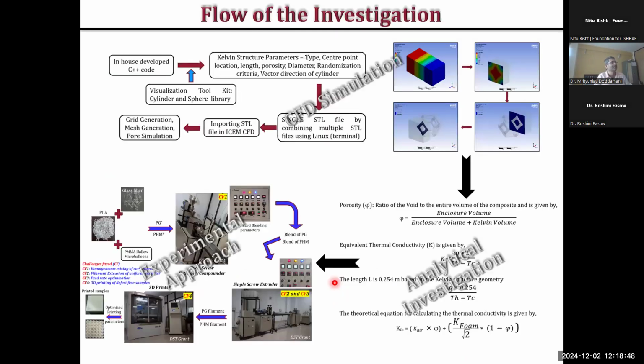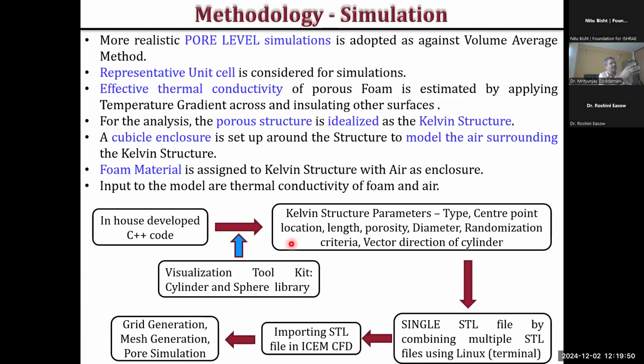And this was the flow of investigation we executed at that time. We started with the CFD simulation, and the basic reason for the CFD simulation is to tap the effective thermal conductivity of a lightweight structure. That is what we did here in a simulation environment. Then we did an analytical investigation, taking the effective thermal conductivity and the volume of a Kelvin structure. What is that Kelvin structure? I'll come back a little later. We can make it out through this as of now. So we took the effective thermal conductivity from the simulation and then went ahead to find out the enclosure volume of this structure we have designed, so that the thermal conductivity can be tuned. And after the analytical investigation, we actually manufactured the component and then showed the actual product outcome of this entire research flow. So this was about this.